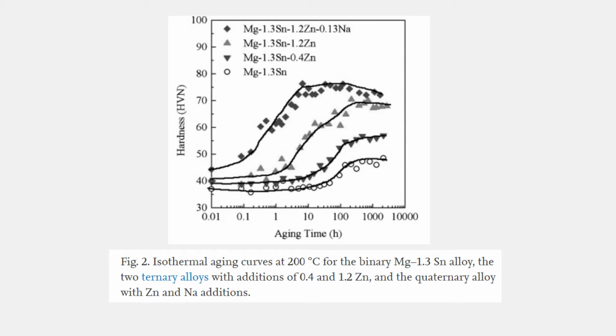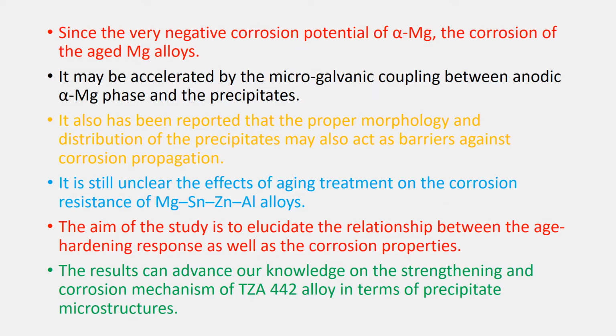This is Figure 2. Figure 2 shows isothermal aging curves at 200 degrees Celsius for the binary Mg-1.3Sn alloy, the two ternary alloys with additions of 0.4 and 1.2 zinc, and the quaternary alloy with zinc and sodium additions. Since the very negative corrosion potential of alpha magnesium, the corrosion of the aged magnesium alloys may be accelerated by the microgalvanic coupling between the anodic alpha magnesium phase and the precipitates.